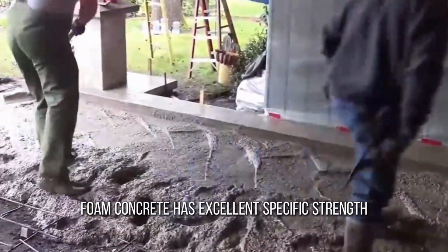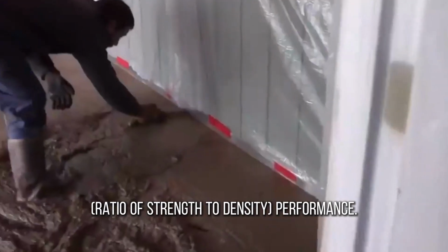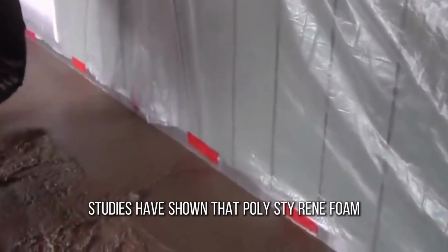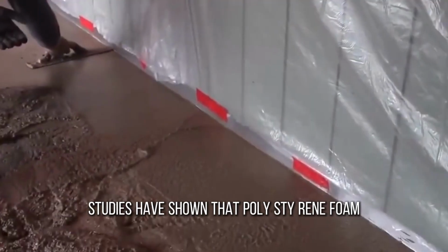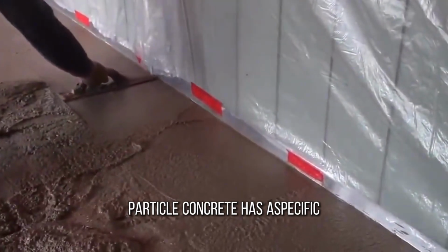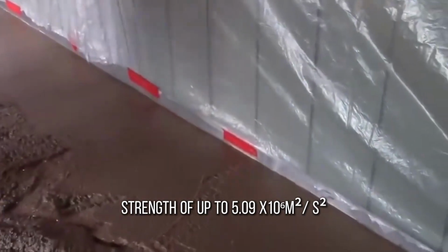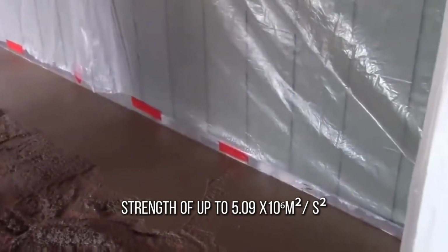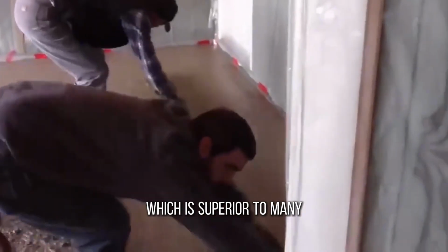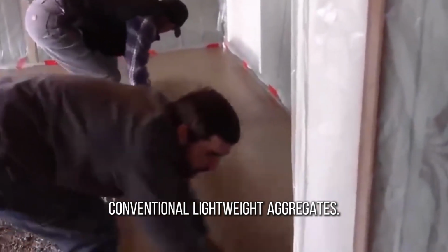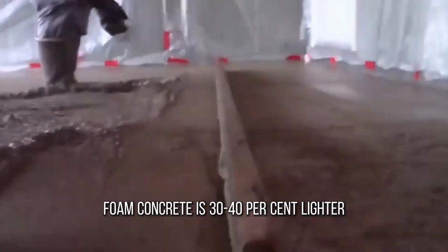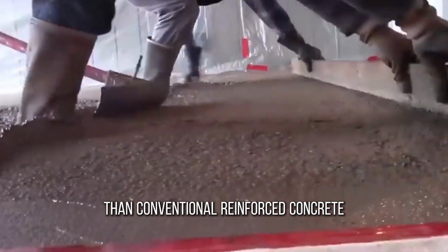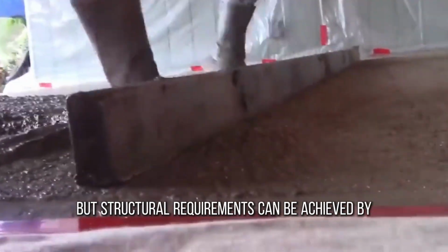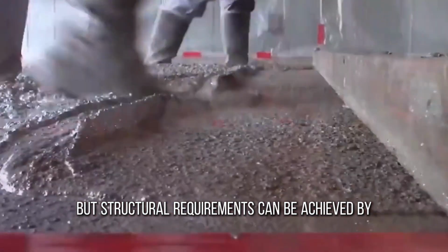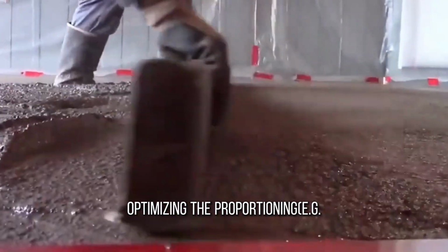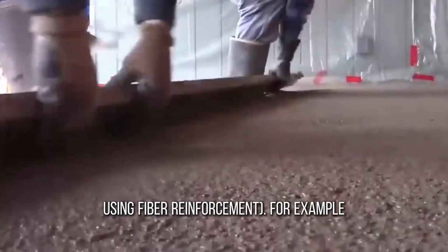Foam concrete has an excellent specific strength, the ratio of strength to density. Studies have shown that polystyrene foam particle concrete has a specific strength of up to 5.09 x 10 to the sixth meters squared per second squared, which is superior to many conventional lightweight aggregates. Foam concrete is 30 to 40% lighter than conventional reinforced concrete, but structural requirements can be achieved by optimizing the proportioning, for example, using fiber reinforcement.